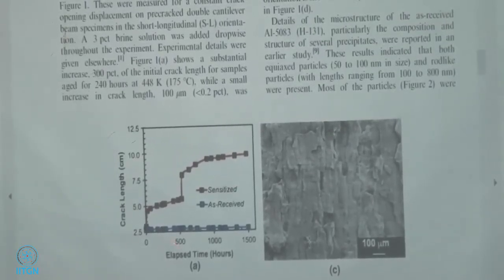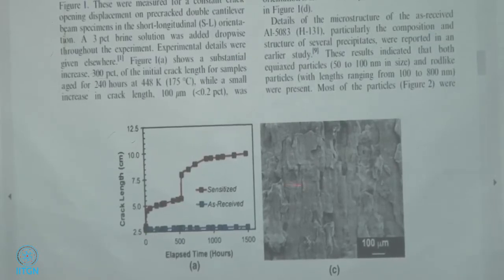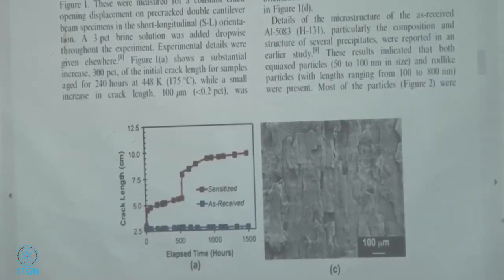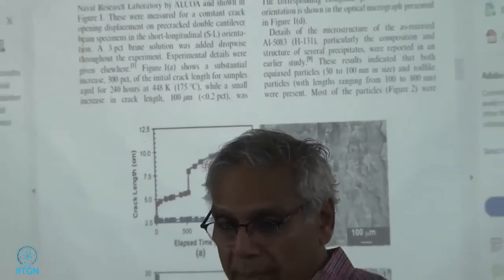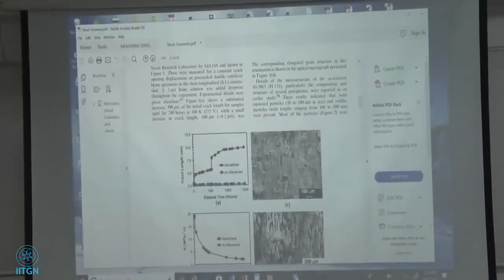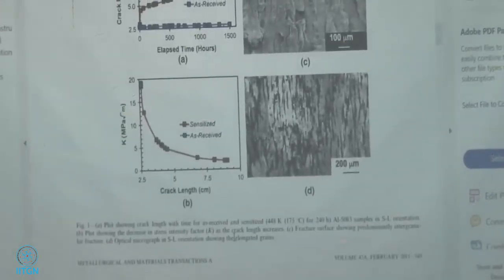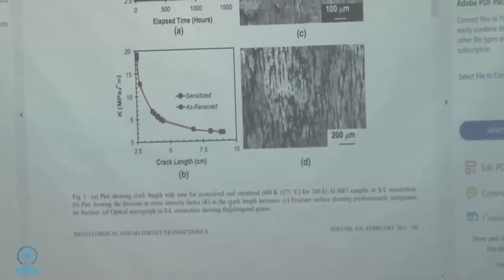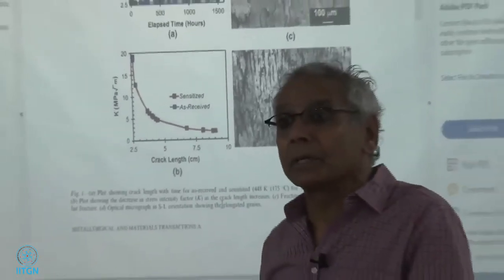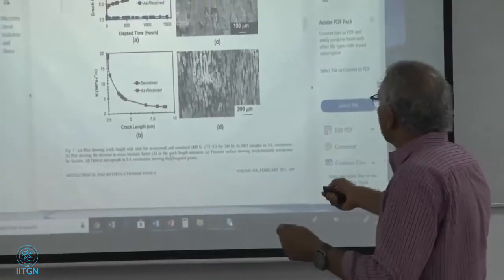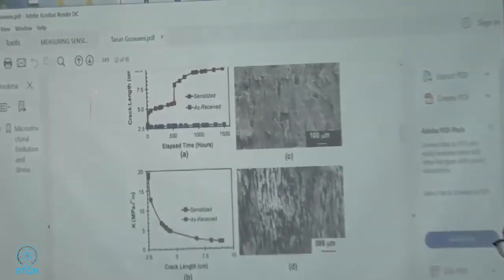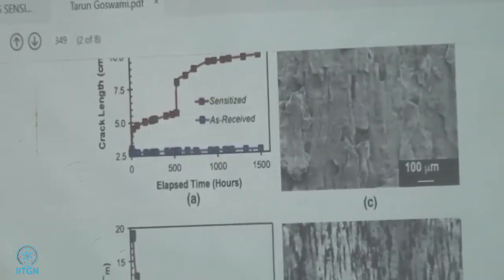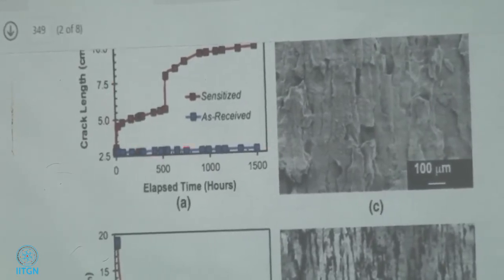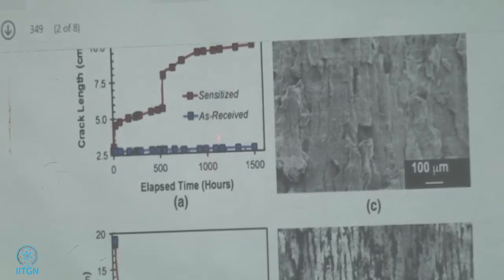So here, let's not worry about this so much. Here is the as received material. Just as received. Here is the one that is sensitized. Anytime you expose a material like this at a certain temperature, I think this was 175 degrees C, if I remember right. It's been about 8 months or so since I've looked at it. Yeah, 175 Celsius. When you expose this material to this high temperature, the precipitates start to fill up the grain boundaries. Okay? You can see that the crack length is increasing as a function of elapsed time. See how long the crack length is.